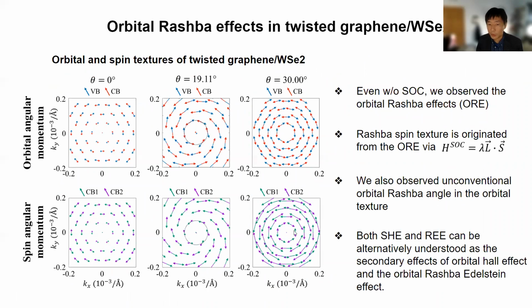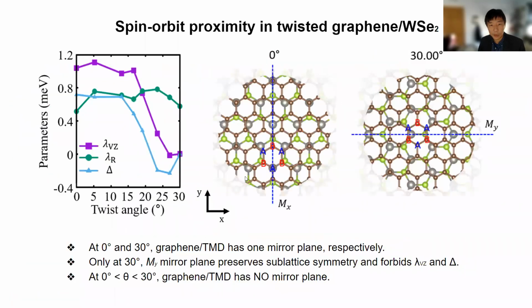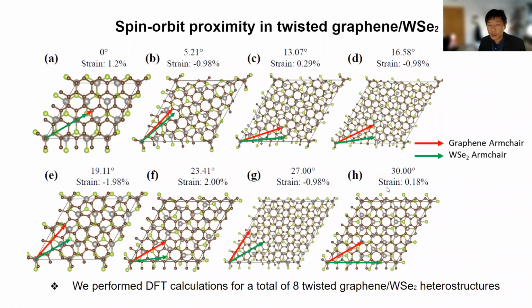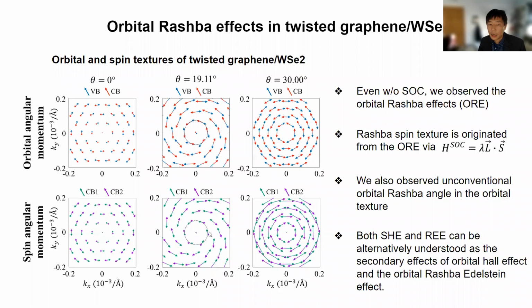So the spin and the momentum are locked at 90 degrees. But for other angles, you see this canting. That has something to do with the fact that the mirror symmetry has been broken. If you look at 0 and 30 degrees, it has this mirror plane symmetry. But if you go to other angles, there's no more mirror symmetry. Because of the absence of that mirror symmetry, this type of spin is now allowed.